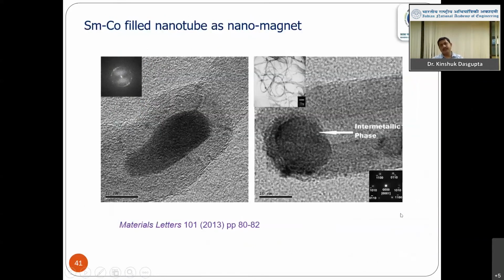There's another interesting application. I'm talking about a tube, so inside is hollow, definitely. So what happens if we can fill some metal into the hollow space? If we put some magnetic material, say iron first of all, they behave in a different way than the bulk material. People have reported single metal insertion inside the cavity, but here what we did, we tried to put bimetallic, like samarium cobalt, SmCo5, which is a very strong magnet. We wanted to see whether we can form that phase inside the nanotube and whether that can be used as a nanomagnet. And we could successfully make the SmCo5 phase inside the carbon nanotube. And the application is there in hyperthermia kind of application.